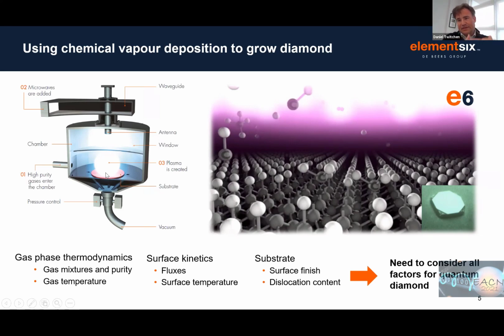The carbon precipitates out of this hot plasma on that substrate, both as sp2 graphitic phases and as sp3 diamond phases. But if the plasma is hot enough, you can produce an awful lot of atomic hydrogen, and that atomic hydrogen etches away the graphite, the sp2 phases, and by default leaves sp3 diamond. So for many, many years, people believed you couldn't grow diamond in this part of the phase diagram, at relatively low temperatures and pressures, because it's a place where the local chemical kinetics beat the local thermodynamic conditions. So you can grow diamond at relatively low temperatures and pressures using chemical vapor deposition.